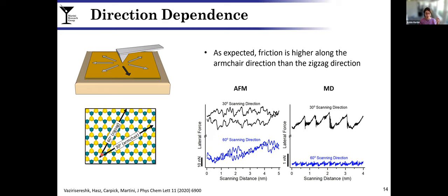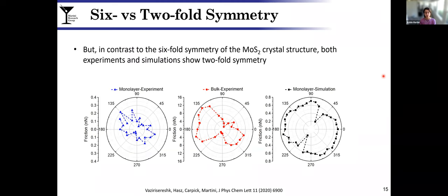Shown here is an example of the kind of friction data that Rob was able to get in his group. Here you're looking at two different friction loops at different directions, both on MoS2, and you can see the characteristic stick-slip pattern, which again indicates that we're able to correlate friction back to the atomic lattice. We found that the direction of sliding relative to the crystallographic lattice has a significant impact on friction. Specifically, if you're sliding along a zigzag direction, you get much lower friction than if you're sliding along an armchair direction.